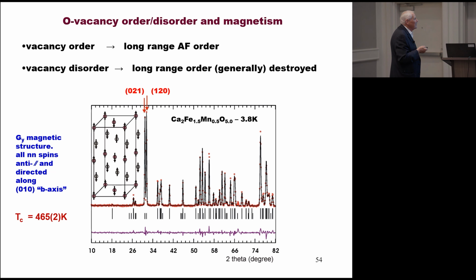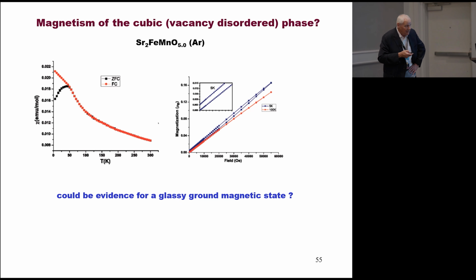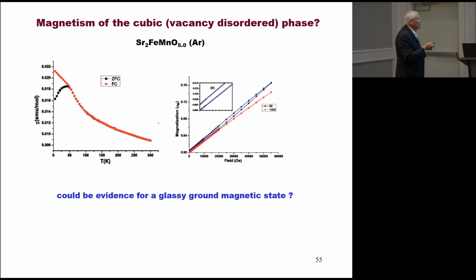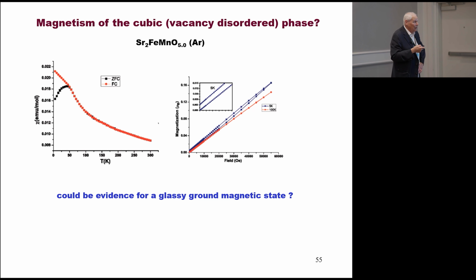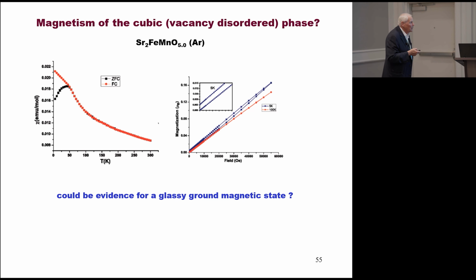Now what happens with the strontium phase? Well, here's a similar susceptibility curve for this Sr2FeMnO5.0 phase. And you see any indication of long-range order seems to be gone. And we get this zero-field-cool divergence somewhere below 50 Kelvin. If you remember what we saw earlier, this looks vaguely like maybe a glassy transition to a spin glass state. But in fact, it's not.